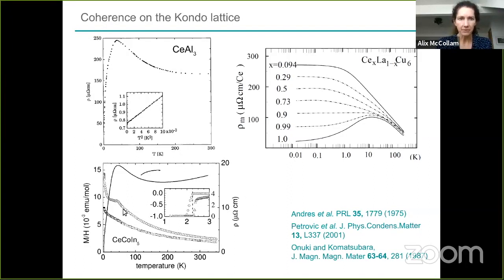This is in cerium cobalt indium 5. This again is the same thing. This is the coherence temperature on the resistivity. This is the axis of resistivity as a function of temperature, and this curve is the resistivity curve. This is the susceptibility, which is given on this axis, and you can see that the Curie-Weiss type behavior that turns into a kind of at least temporary saturation of the susceptibility coincides with the coherence temperature also here. So these two happen around about the same temperature.